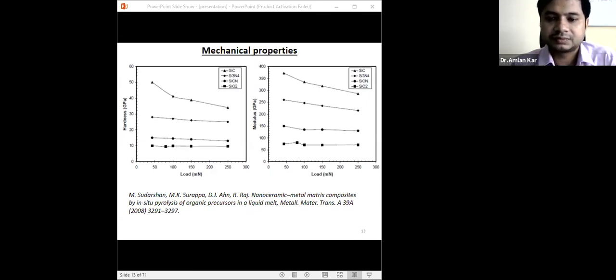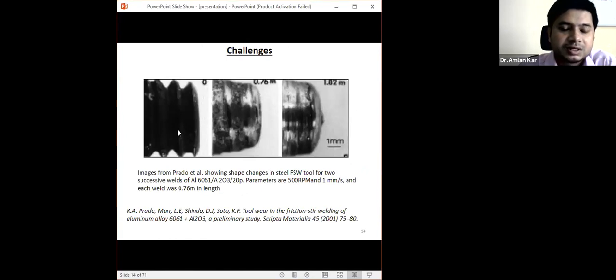So here you can see, this is the main challenge in the case of ceramic matrix composite. Therefore, if you directly incorporate the ceramic particle in the matrix and then you do the processing, it is very difficult to obtain a homogeneous property from the beginning to the end of the process, because depending on the length of the process, the features of the tool change. Because of the change in the tool features, there is a change in the mixing of the particles in the matrix, and therefore there is a possibility of a difference in the physical property of the material.